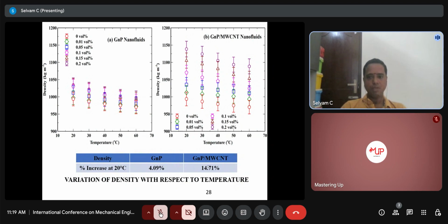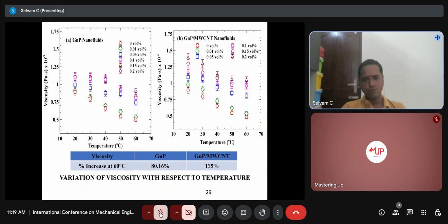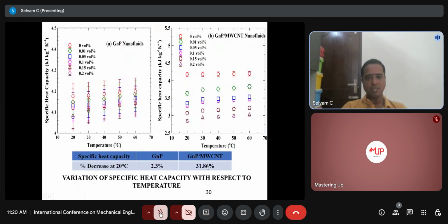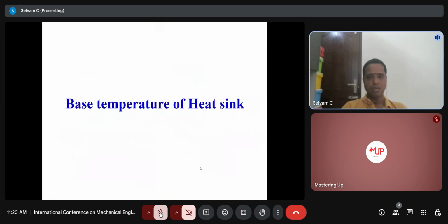And viscosity is similar to density. With respect to GNP, I mean graphene nanoplatelets, we have observed an 80.16% increment in viscosity, while the increase in viscosity in the hybrid nanofluid is 155%. Specific heat capacity is reduced with respect to the volume concentration of the nanoparticles. With respect to GNP, a 2.3% reduction has been observed, and Cp is reduced up to 31.86% for the hybrid nanofluids. And these are the results of the convective heat transfer study.